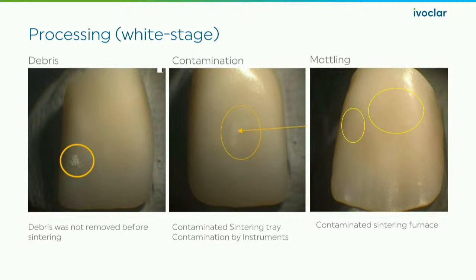So remember, we're starting at about 25% larger. And as this is going through the sintering process and organics are burning out, when the material's shrinking, what happens is that speck of whatever, it could be aluminum oxide because the last thing you did was sandblast something. You've got hairy arms like me, it falls off on the bench and you pick it up and you have it on your hand and it's on the crown. That little speck of aluminum oxide gets pulled into the surface. And what it does is it acts as a separator to the crystal structures forming. So basically it just kind of works its way down and you'll see the disruption from around where that is.